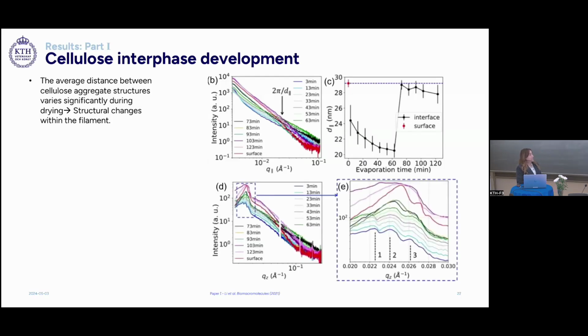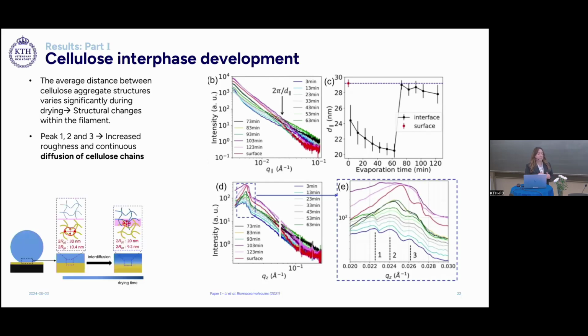When looking at the intensity curves obtained from the vertical integrations of the 2D patterns, we can see that we have 3 different peaks. Peak 1 is obtained when the wet filament is placed on the cellulose film, and therefore is attributed to the newly formed interface between the 2 materials. And peak 2 is attributed to the surface of the cellulose thin film. When we increase the evaporation time, we can see that the peaks broaden and shift to the right, which means that we have increased roughness and continuous diffusion of cellulose chains in the interface.